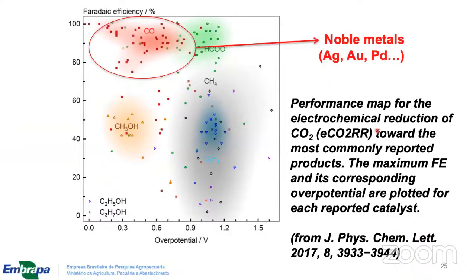We know that carbon monoxide production can be achieved using some different noble metals, especially silver, which is one of the most interesting so far, with an adequate overpotential. But to make other products, binding the carbon with hydrogen, we need to use other materials, especially copper and copper oxides. So the problem is still the overpotential that we have for these systems. But so far, the most promising material is certainly copper oxide, because this is almost stable. We have a good equilibrium in terms of price. The recovery of the catalyst is still easy, but we are still